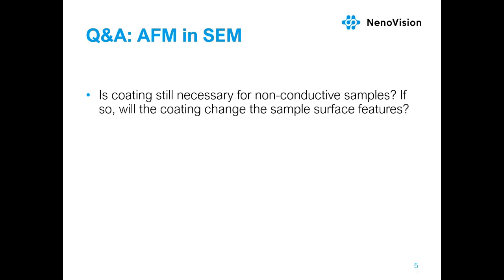Will it change the sample's features? Of course it will, because if you place on your sample 2-3 nanometers of gold or platinum, first of all you modify the topography a bit. Then it depends on the size of your features. If it's 200 nanometers, then 100 nanometers doesn't matter that much. If you are talking about a 1 nanometer size particle, yeah, then it matters. But you also change the mechanical property a bit and you change the conductive property. So coating influences the sample. And it's needed because of the SEM. It's not needed for the AFM analysis.